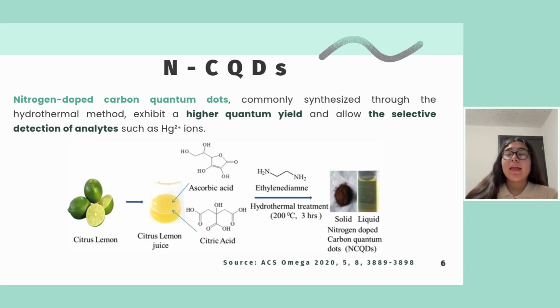As previously mentioned, carbon quantum dots can be functionalized through doping, with nitrogen being one of the most commonly used heteroatoms, due to its ability to enhance the optical properties of the materials. An example of this was reported by Teruel and co-workers, who synthesized carbon quantum dots using lemon citrus juice as a precursor and ethylenediamine as a doping agent. The authors observed that nitrogen doping increased the quantum yield, a parameter associated with photoluminescence efficiency, and improved detection selectivity toward different analytes.